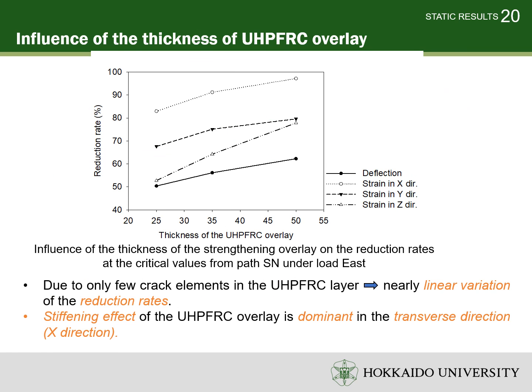The influence of UHPFRC overlay thickness on the reduction rates at critical values of deflection and strain obtained from the path SN is also investigated and shown in this figure. The thicknesses of UHPFRC layers chosen for the parametric study are 25, 35, and 50 mm. As can be seen from the figures, the percentage of reduction in deflections and strain values linearly increases with the thickness of the UHPFRC overlay.